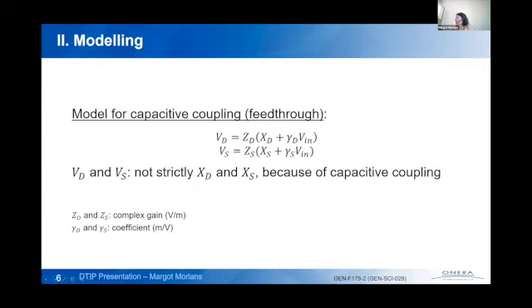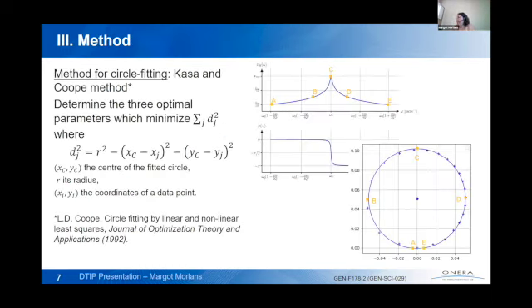We can see that the output of the drive mode isn't only XD, but there is also a bit of capacitive coupling here. So we have a small amount of V in. So this is not a rotation. It's not due to misalignment in electrodes or any design errors. It is really due to a small capacitance between pins on the cell.